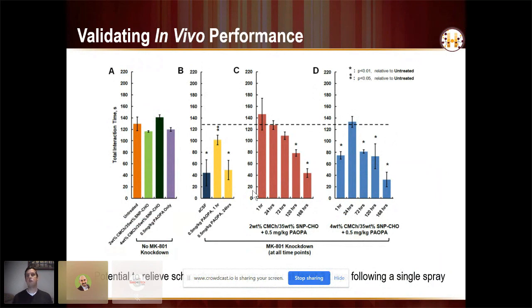If we administer PAOPA, the drug, through the nose just alone, after 1 hour, we recover most of the behavior. After 24 hours, there's no residual benefit at all. So if we deliver the same dose of drug using our hydrogel, and in particular, the lower dose carboxymethylchitosan hydrogel, which again has a much better spray property, we see we can relieve the schizophrenia symptoms entirely for 72 hours and with still some residual positive effects out to 5 days.